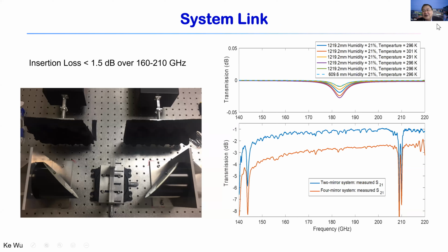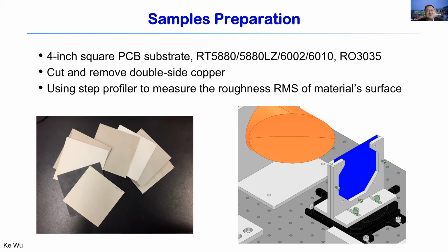By the way, if you look at this, the contribution of the humidity and even temperature put together actually changes a little bit here. So that's very delicate. I said the 180 gigahertz band, roughly 183, 185 gigahertz frequency range. You have to be careful. In this frequency range, measurement can be significantly affected by variation in humidity and temperature, particularly if you want to accurately extract the loss tangent in this frequency range. So that shows again this measurement setup, how we have to guarantee the accuracy in the system.